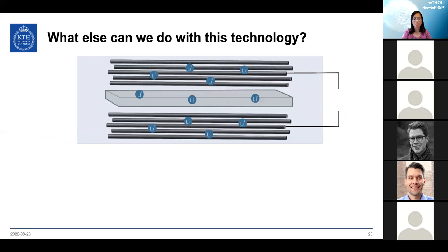Here we see a 3-layer composite with 2 layers of carbon fibers and a separator, all of which are in the structural battery electrolyte. The carbon fibers are activated with lithium ions to 50% of their total capacity. Now, running a current from one side to the other means we are moving the lithium ions from the carbon fiber on one side to the other.